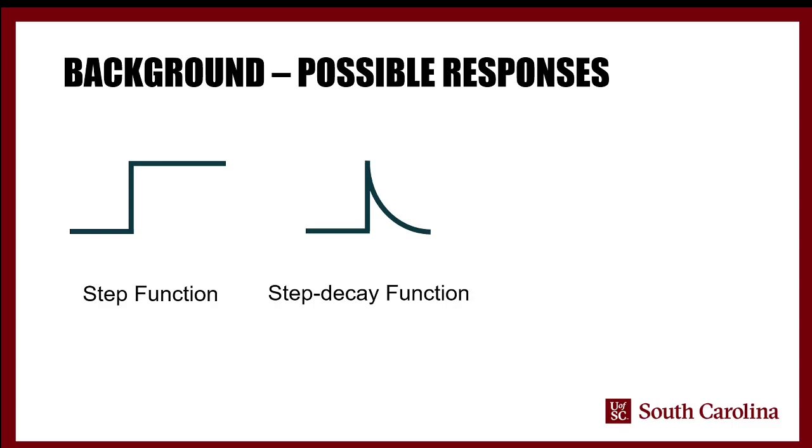First, it can mean that the particle hits, performs some catalytic reaction, and then the particle itself dissolves. It can also mean that a particle hits and continues to stick but is deactivated. An example would be a hydrogen evolution catalyst that hits and sticks, and starts to evolve hydrogen from a proton solution, but the bubble sticks on the catalyst. If the bubble is big enough, it can block the catalyst from any further reaction, and what you observe is the same as if the catalyst was completely deactivated. So until that bubble falls off, it will deactivate the catalyst.